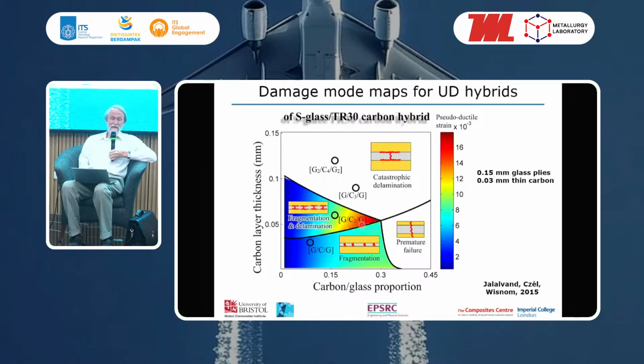So the red here is the highest: 0.15 millimeter glass plies, standard thickness glass plies, but these thin 0.03 millimeter carbon plies. If we have 4 of these 0.03 millimeter carbon plies, in other words that's about 1 standard carbon fibre ply, you see we're in the delamination regime. And as we reduce the number of carbon plies, we get closer here. When we go to 2 carbon plies or 1 carbon ply, we're in this pseudoductile regime.